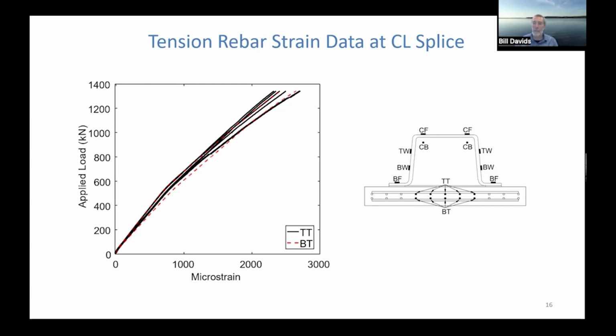So we spec'd 60 KSI steel. We actually got a higher grade of rebar, which is not unusual for the actual yield strength to be a good deal higher than the nominal value. And this is why the capacity of the specimen, one of the reasons why the capacity was so much higher than what we expected it to be.